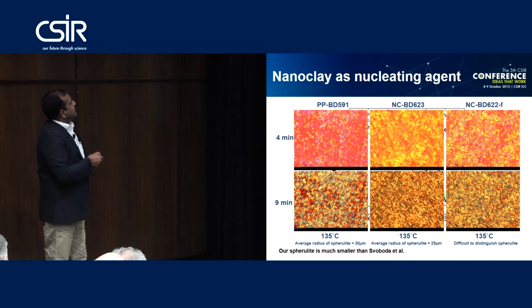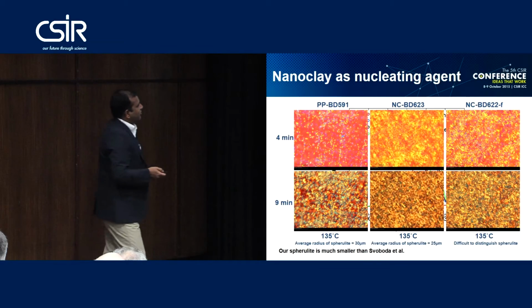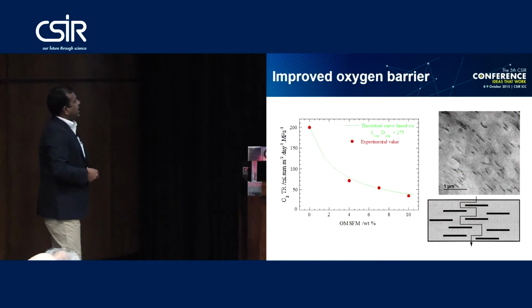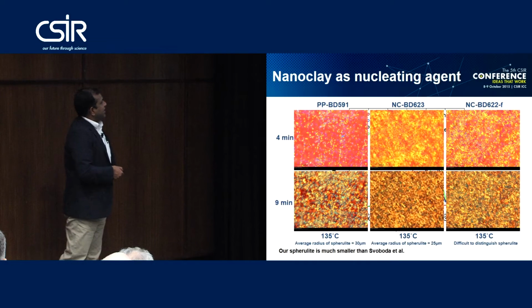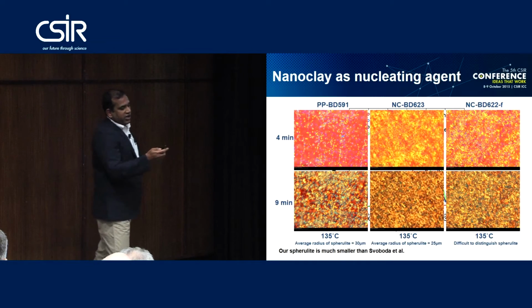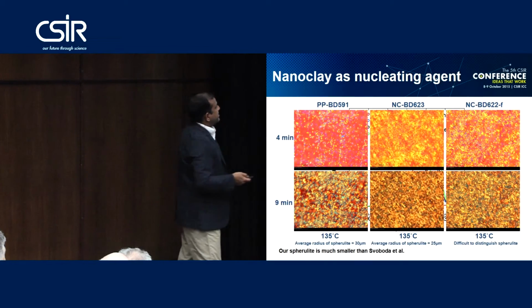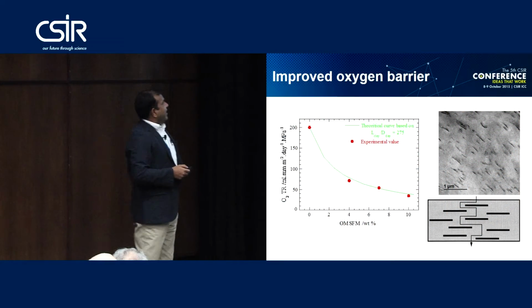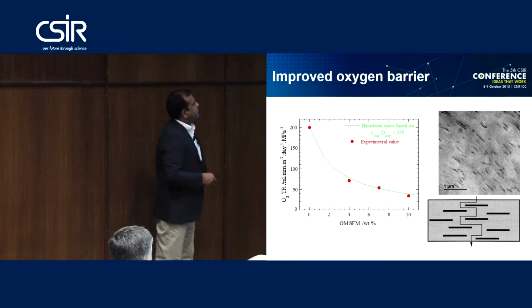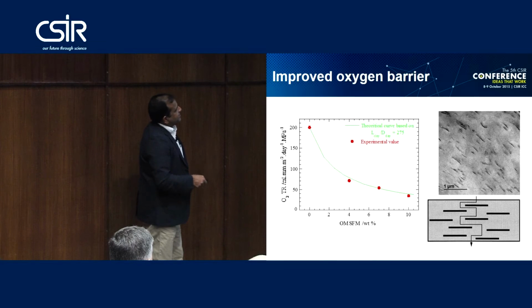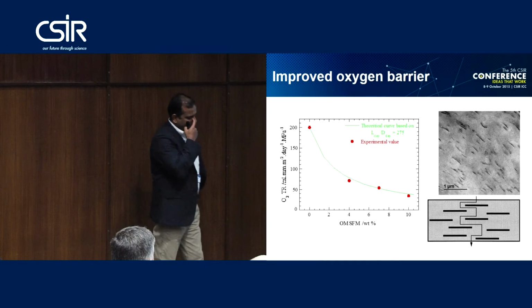So you can see this is the normal polypropylene, and this is a nanocomposite, nanoclay-containing polypropylene. This is actually much higher than the now commercially available filler for improving the crystallization temperature. And finally, some examples of how you can decrease the permeability of gases.